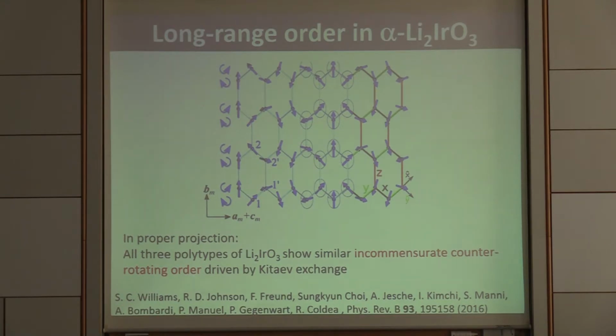In the lithium iridate, on the other hand, we have a very different kind of ordering. We have a non-coplanar incommensurate counter-rotating order, a very complicated arrangement of the moments as indicated here. But there as well, the Kitaev-type interaction is very important, which can be seen by looking at these different bonds. For instance, the black bonds here are the X bonds. For two spins on X bonds, we always have a parallel spin component along the X direction, as seen here. The same holds also for the Y and the Z bonds, and that is the indication for this ferromagnetic Kitaev-type exchange between nearest neighbors, which is important in this material.